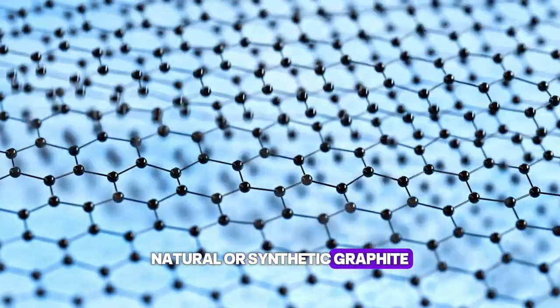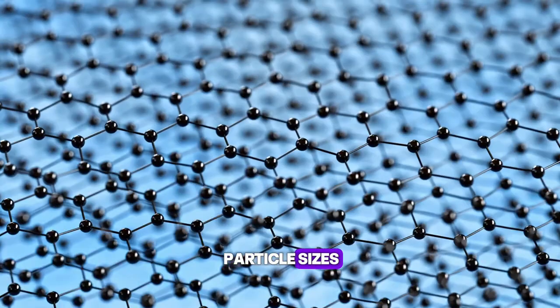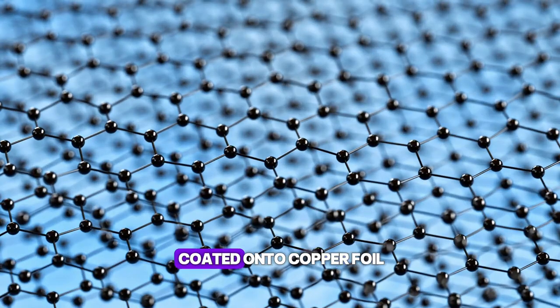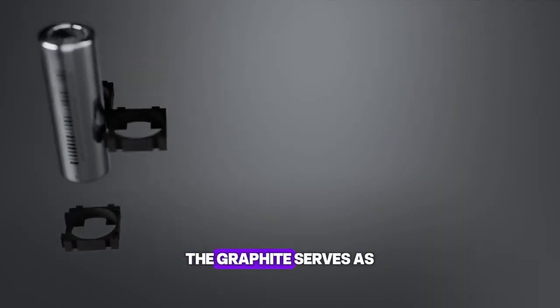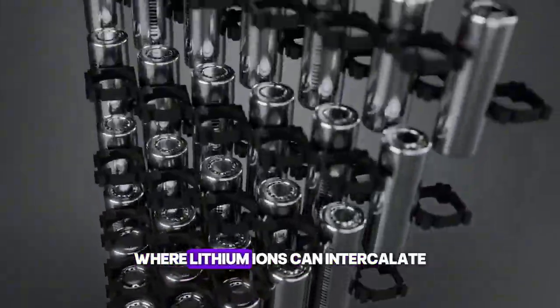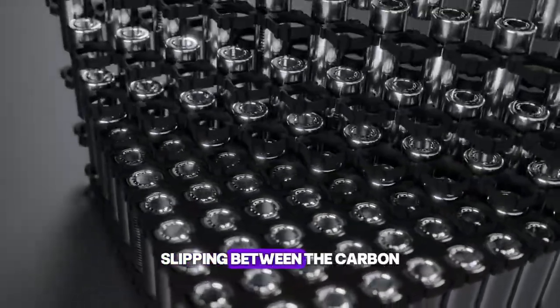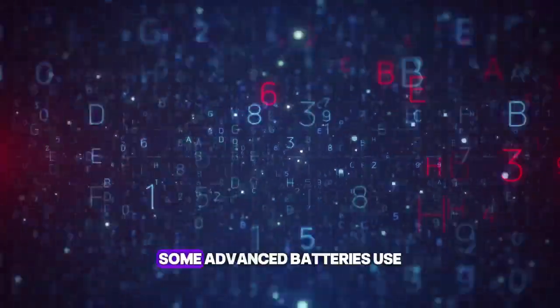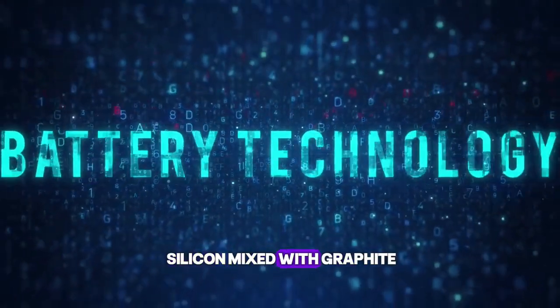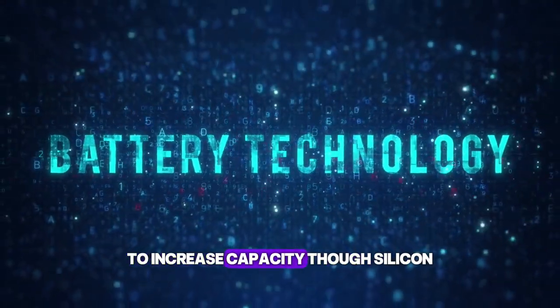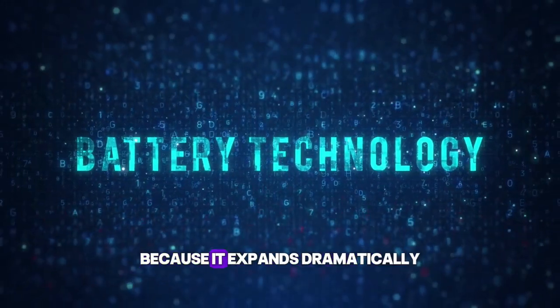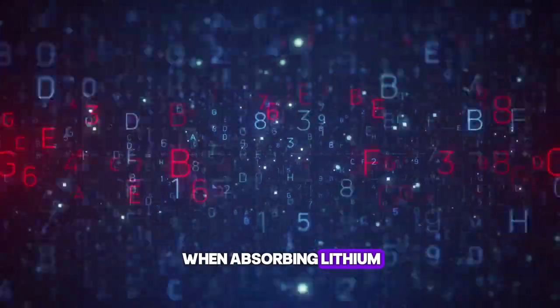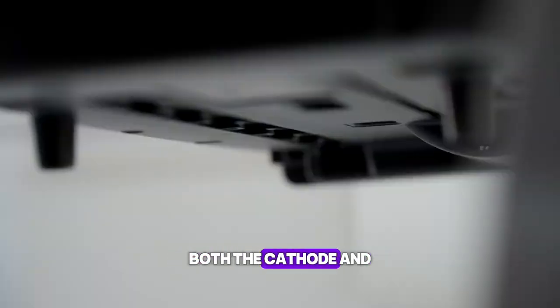Natural or synthetic graphite is ground to precise particle sizes, mixed with binder, and coated onto copper foil. The graphite serves as a host structure where lithium ions can intercalate, slipping between the carbon layers during charging. Some advanced batteries use silicon mixed with graphite to increase capacity, though silicon presents challenges because it expands dramatically when absorbing lithium. After coating and drying, both the cathode and anode sheets are cut into precise dimensions.